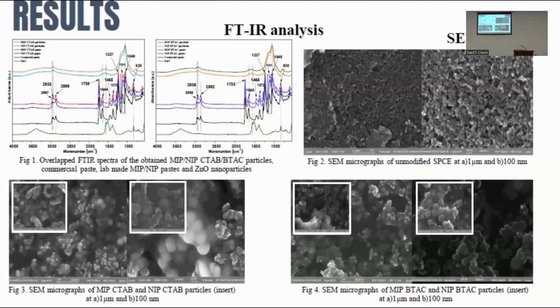As exhibited in figure 2.4, there are clear differences between the morphologies of the unmodified and modified prepared surfaces of the electrode. A smoother specific surface for the bare electrode is revealed, while spherical or irregular microparticles and nanoparticles or aggregates distributed homogeneously as a polymer layer on the SPCE are observed. As expected, SEM confirmed the incorporation of polymeric particles in the carbon paste, well dispersed into the matrix, as well as some nanorods or irregular hexagonal bodies characteristic to zinc oxide particles, and a much more porous structure for the MIP sensor compared to their homologs.